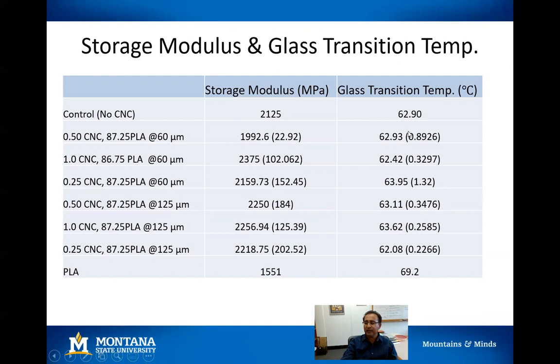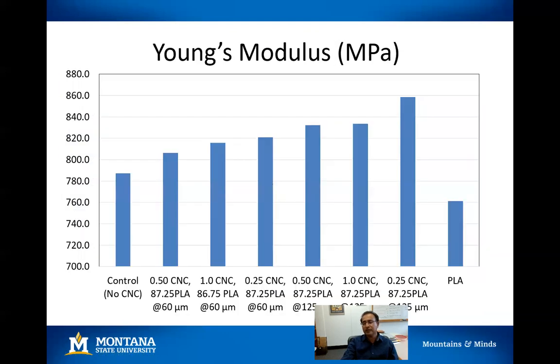But on the other hand, if you look at the glass transition temperature, the commercial PLA has a glass transition of 69.2, but when we added plasticizer, DDGS, and CNC, the glass transition dropped from 69 to almost 62.91. And part of that is because we are using the plasticizer that has an impact on this.